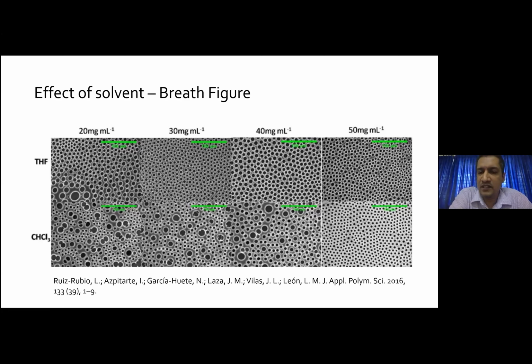The viscosity is due to the solute, that is, the polymer dissolved in the solvent, whether it is THF, chloroform, benzene, or whatever it is. So the flow rate has to be chosen depending upon what kind of solvent and what kind of polymer you choose. Depending upon that, you can control the morphology and the pore dimensions of the polymers.